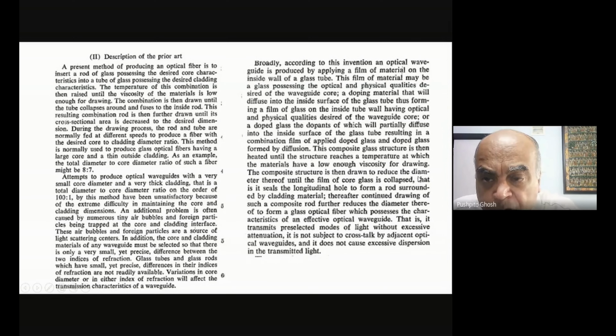The composite structure is then drawn to reduce the diameter thereof until the film of core glass is collapsed. That is, it seals the longitudinal hole to form a rod surrounded by cladding material. Thereafter, continued drawing of such a composite rod further reduces the diameter thereof to form a glass optical fiber which possesses the characteristics of an effective optical waveguide. So first you create an inner film so that there is a refractive index differential. Then you start softening the material and drawing, letting the film collapse into a rod. And thereafter you keep drawing to get whatever final diameter of the optical fiber you want.